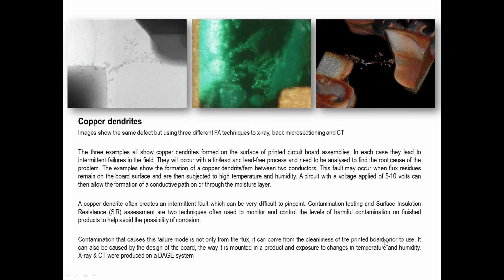Now, another thing that we started to see during the introduction of lead-free technology is more examples of copper dendrites or corrosion. Now, I have to say, a lot of people blamed the new materials, and lead-free flux was bad because in all honesty, a lot of it was due to poor profiling to start off with. Just like with wave soldering and selective soldering, if you don't introduce sufficient heat as part of the process of reflow, we can actually still have some material which is present, which is still volatile potentially, and also can be conductive if exposed to voltage and humidity.